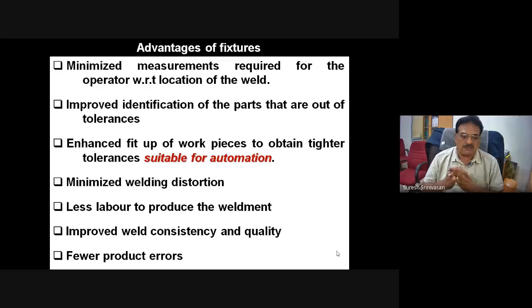For successful robotic automation, fit-up is the most important factor required, because fit-up tolerances have to be very closely maintained; they cannot normally exceed the robot welding wire diameter. If the wire diameter is normally 1.2 or 1.6, generally you have to keep the tolerances within 1.6 millimeters. If the tolerances exceed 1.6, your productivity or arc-on time will reduce. Sometimes the robot itself can give you lower productivity than manual welding because of poor fit-up. Because the robot cannot recognize the deviation, it will simply weld, producing a poor quality weld.